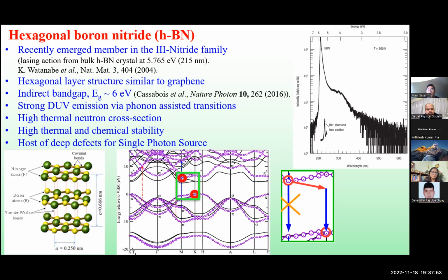And finally, it is proved that it is an indirect bandgap semiconductor, and the strong emission is actually because of the phonon-assisted emission. So I will discuss it in a little more detail later. And hexagonal boron nitride is different from gallium nitride and aluminum nitride. Its crystal structure is different. It's a layered hexagonal structure. It is similar to graphene.